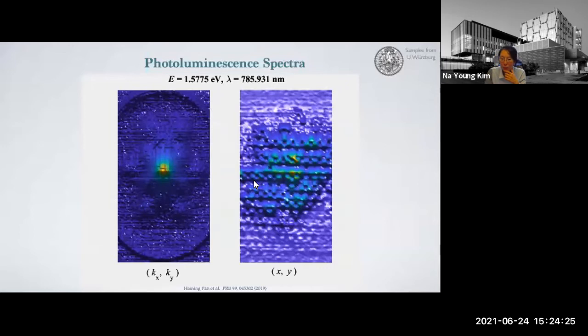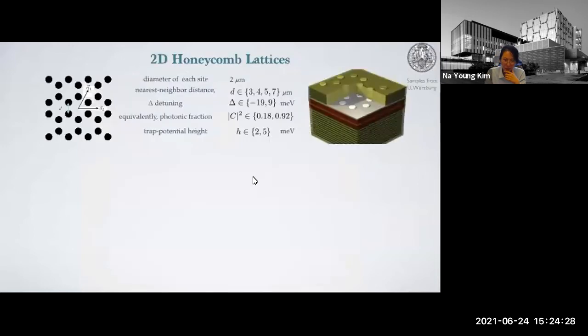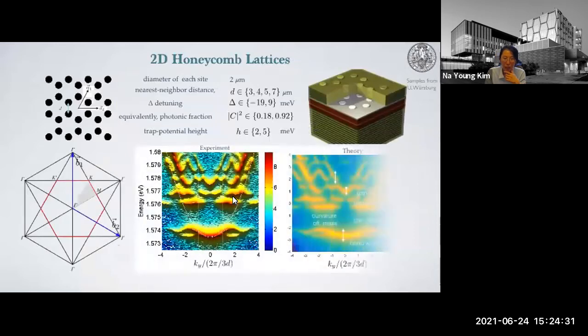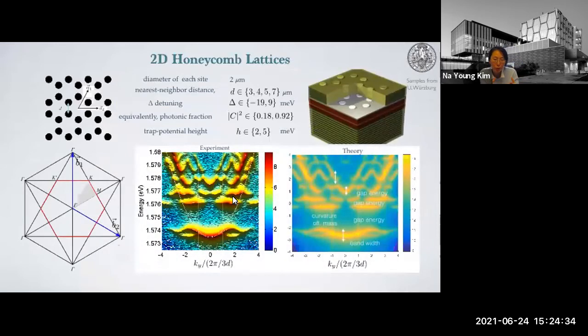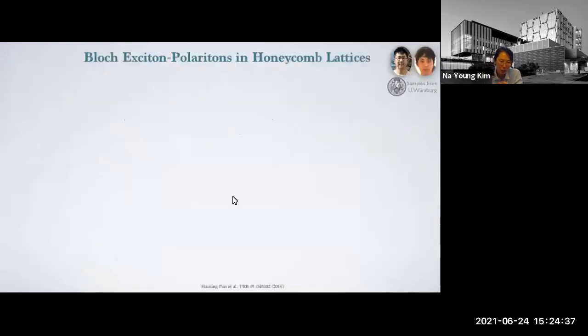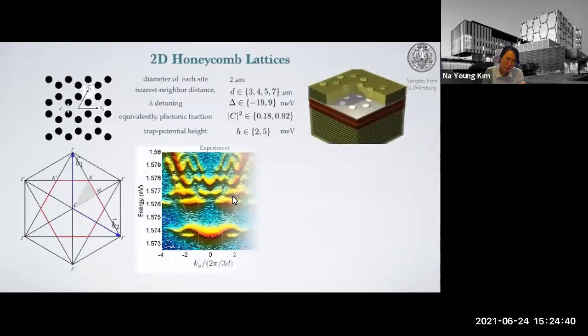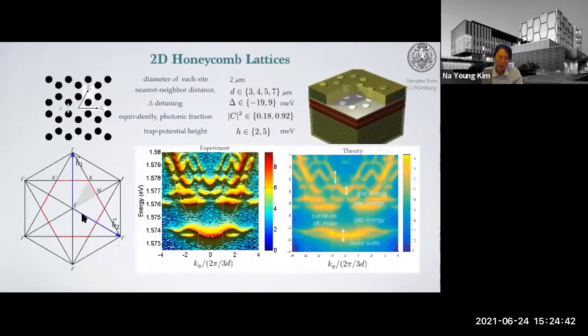Once we have the spectra, what we do is this. In the honeycomb structure case, there's also the honeycomb Brillouin zone, with its symmetry points. And we slice along this particular direction. This is the energy and momentum, which we call the exciton band structure. The middle is the actual experimental data, and on the right are the theoretical simulation results. You can see that we are able to reproduce what we observe in the experiment.